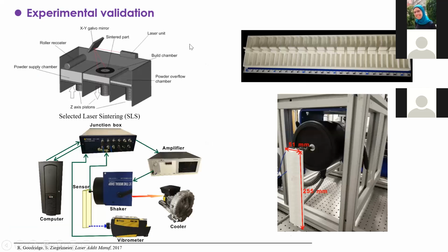We conducted experiments to validate our theory. We manufactured some samples by an additive manufacturing method. Selective laser sintering is one of the most popular additive manufacturing technologies. This method uses powder to create these samples. The powders are put in a chamber and then transferred to this moving plate. A laser is used to sinter the part layer by layer, and finally reach our designed samples, like this.